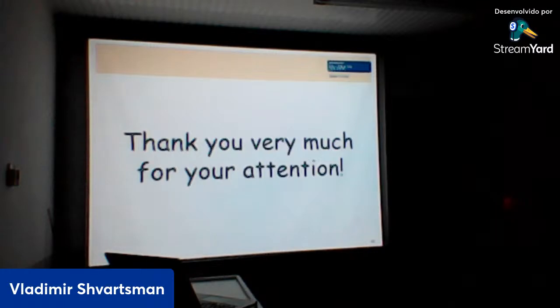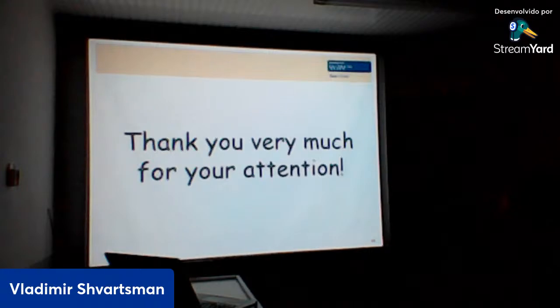My curiosity is about the size of the ceramic particles or nanoparticles to be used in those polymer composites. Typically we deal with nanoparticles, and there is usually an interplay. From one side, you would have to have a particle with large dielectric permittivity, and you know there's a size effect: as you decrease the particle size, your dielectric permittivity will also go down. From the other side, you would like to have really good distribution of nanoparticles in your polymer.